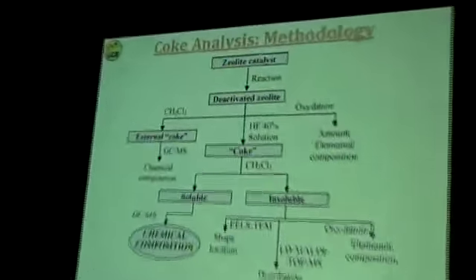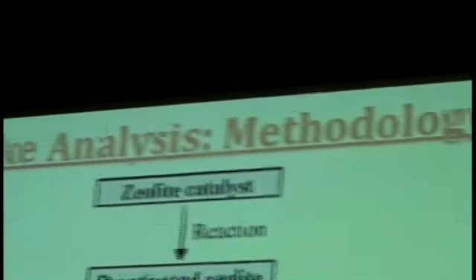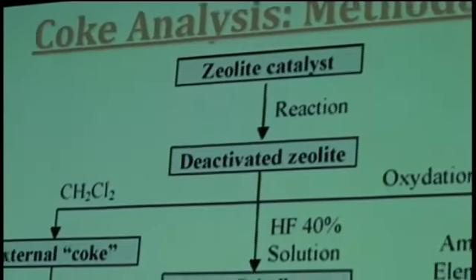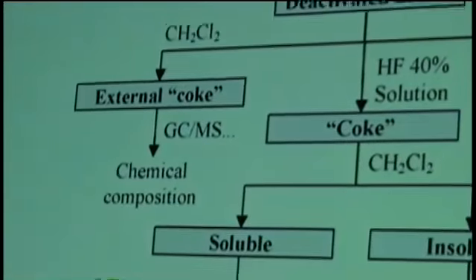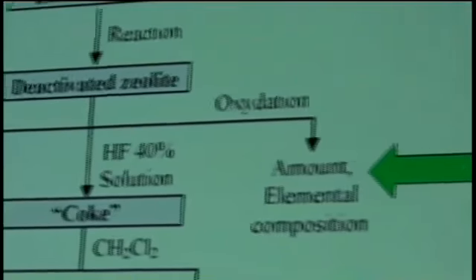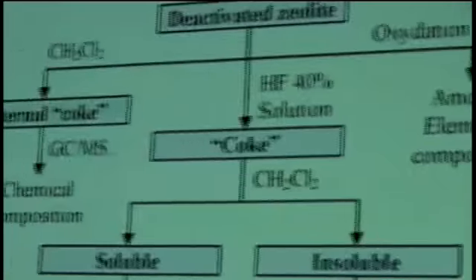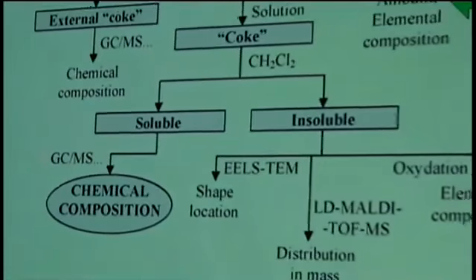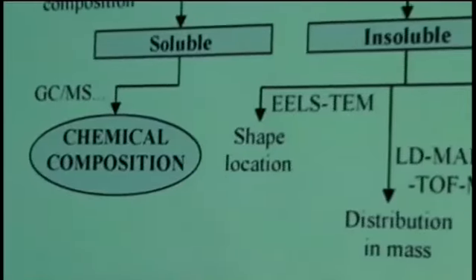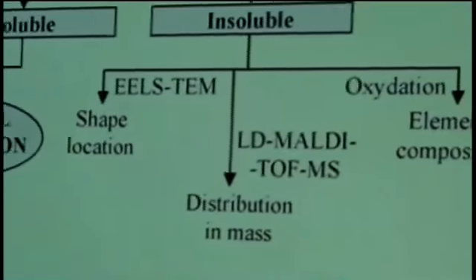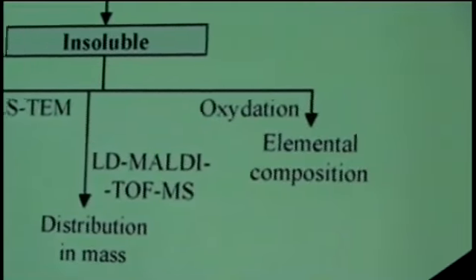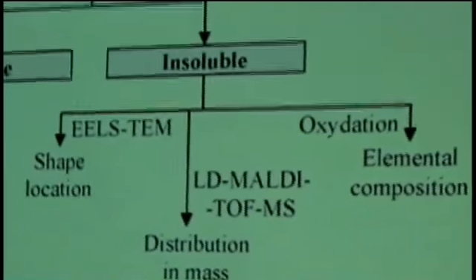So you have the zeolite catalyst, you put it in a reactor, you do the reaction for a certain time, and then you remove the catalyst from the unit, and the first thing, of course, that you are going to measure is the level of coke. The second thing is that you try to wash your catalyst with CH2Cl2, and there basically what you do, you just peel off the coke that is on the external surface or in the mesopore of the catalyst. Okay? So you don't in fact attack the coke that is deeply inside the zeolite.